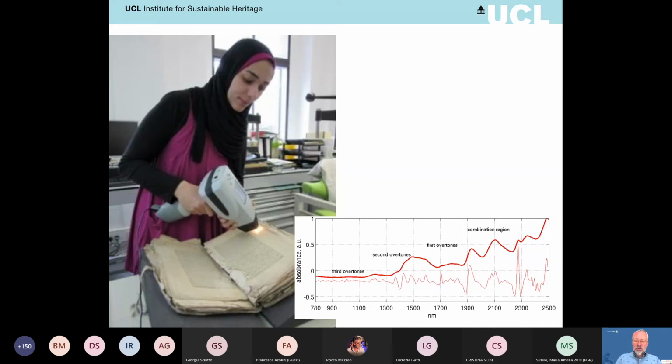They contain just a small number of peaks. But what is important in NIR spectroscopy is that those peaks can be modeled using multivariate calibration, and that chemical properties of materials, such as degree of polymerization or acidity, can be modeled on the basis of spectra that can be obtained using fairly simple handheld portable instruments. Some of those instruments are available in the IPERION HS catalog.